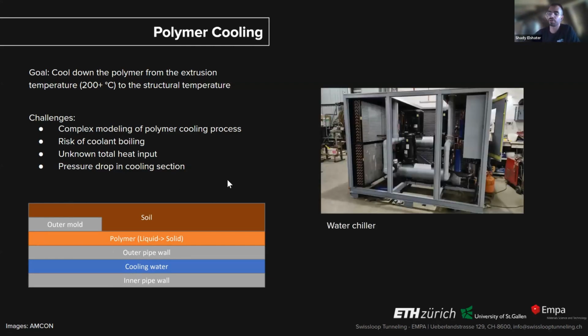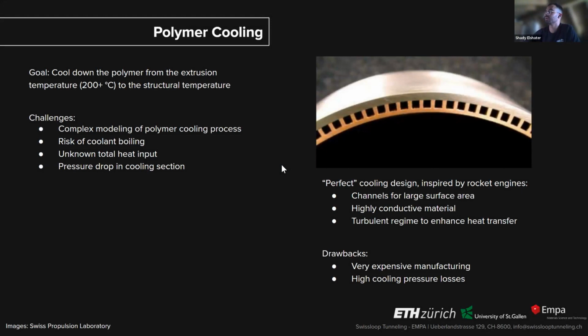In our case, we just connected our system to a water chiller, which has a closed loop, brings the cold water to the system, and then the hotter water back, and it's cooled down. To connect to this challenge, if you really wanted the perfect cooling system, the design would have some kind of channels with large surface area, highly conductive material, and a turbulent regime to enhance the heat transfer. Here you can imagine that it's not so different from our system. We would just have the polymer here on top. This would be the perfect system, but it's obviously very expensive to manufacture, and you also have high cooling pressure losses. But these are at least the things to keep in mind. So the surface area and the turbulent regime are the most important things.